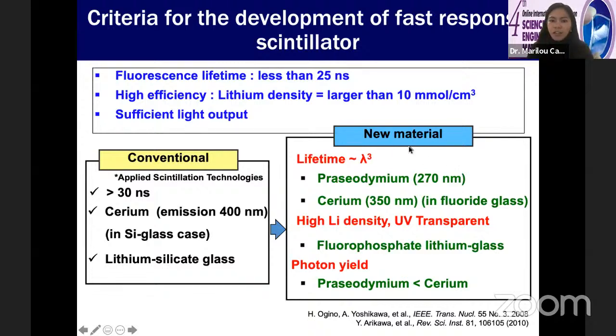So for the new material that we developed, we used praseodymium and cerium ions as the activator ions that produce the luminescence. The main consideration for using these activator ions is their emission wavelengths. We found that the shorter the emission wavelength is, the faster the decay time and the response time is. And so we use praseodymium and cerium as the activator ions. For the host, we chose to use fluorophosphate lithium glass as the matrix. Lithium has to be present because that's where the lithium-6 comes from. And it's also transparent in the UV region. We chose to use glass. Of course, we can use crystals as well, but glasses are more economical to fabricate.